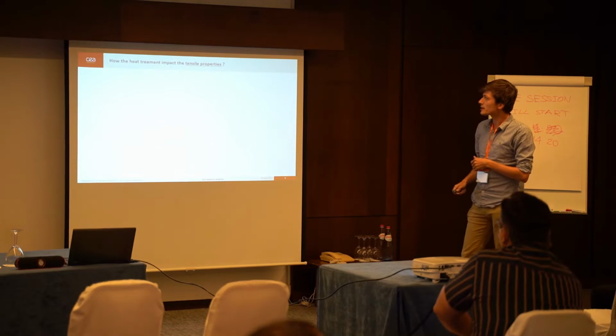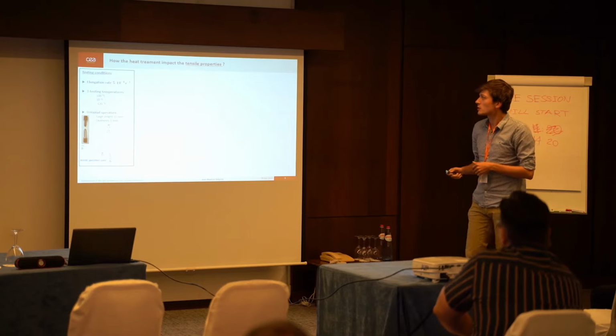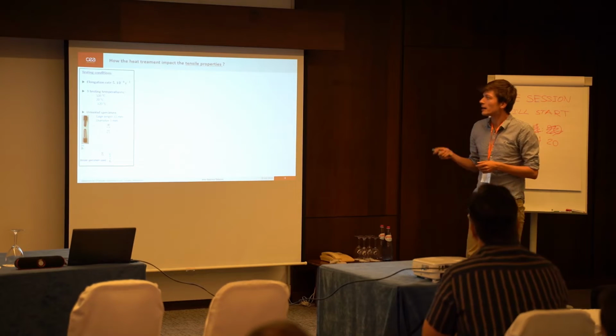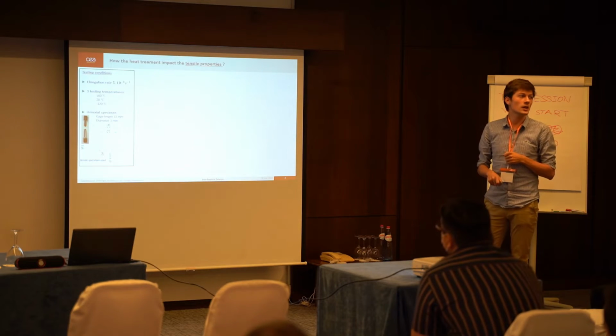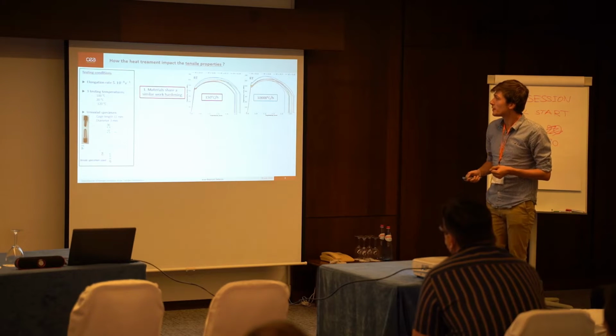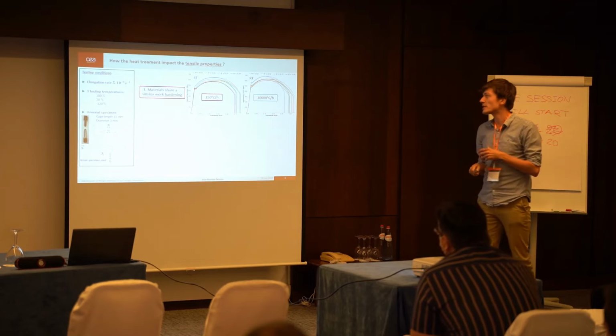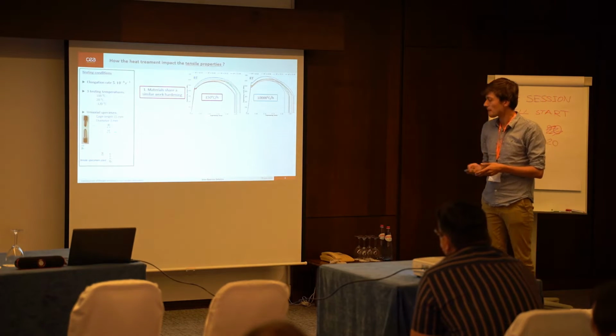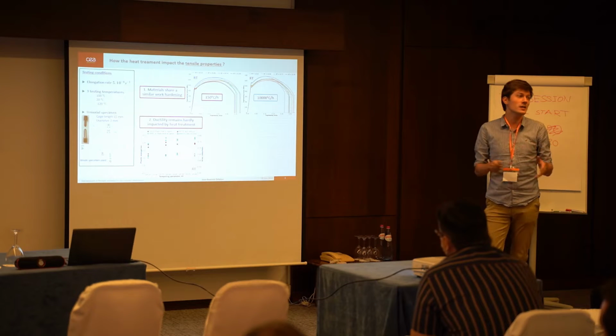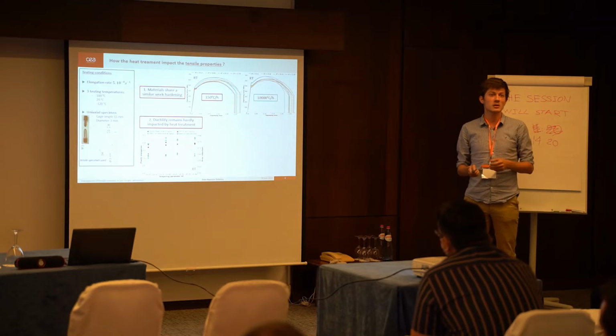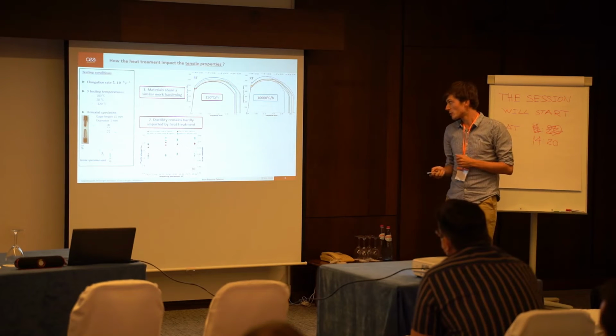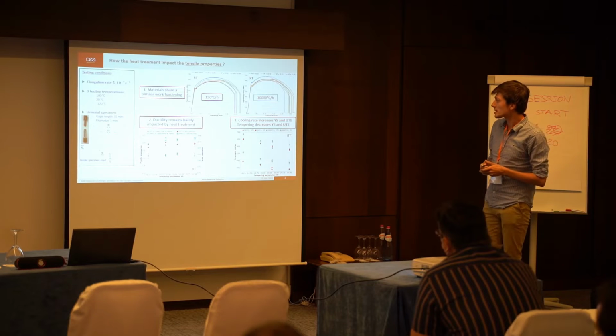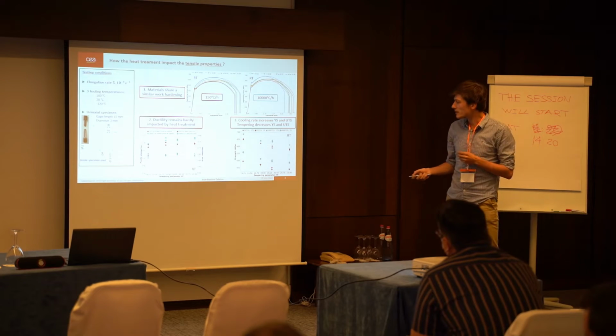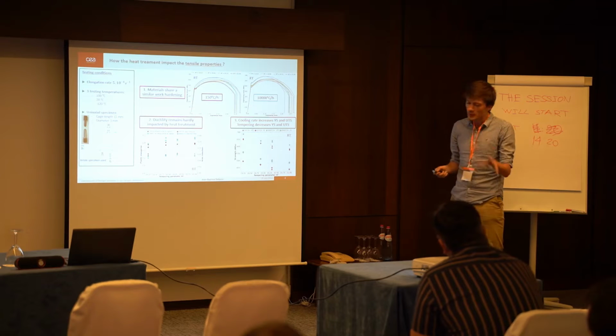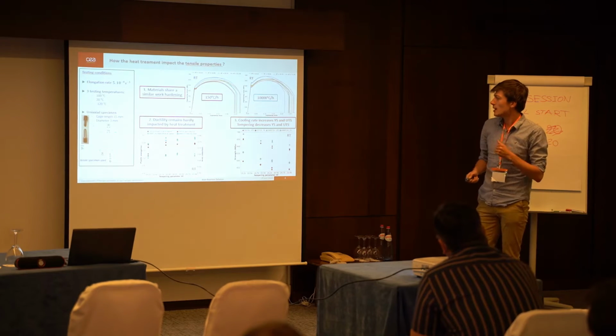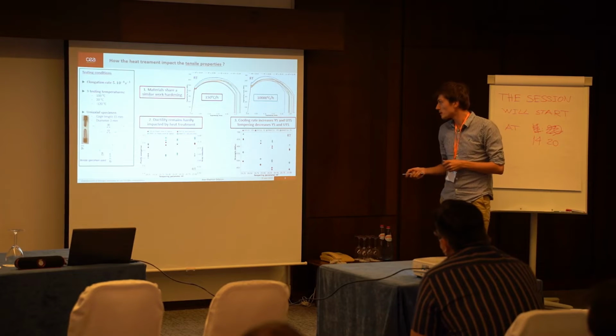So now if we look at the results, first for tensile properties. We have done the tensile testing at 3 different temperatures, but here we will just look at the result at room temperature. First, the materials seem to share a similar work hardening behavior. Ductility remains hardly impacted by the heat treatments, both for the plastic elongation at rupture and the reduction of area at rupture. The cooling rate increases both the yield strength and the ultimate tensile strength by around 50 MPa, and tempering decreases both yield strength and ultimate tensile strength by the same order of magnitude.